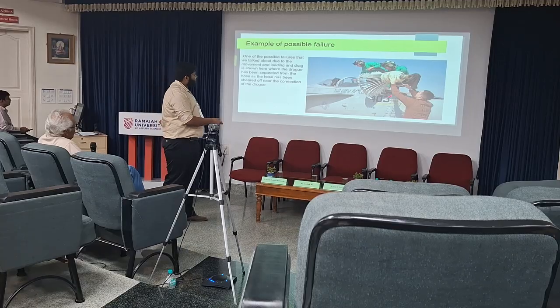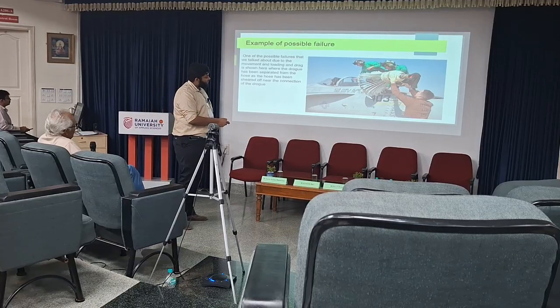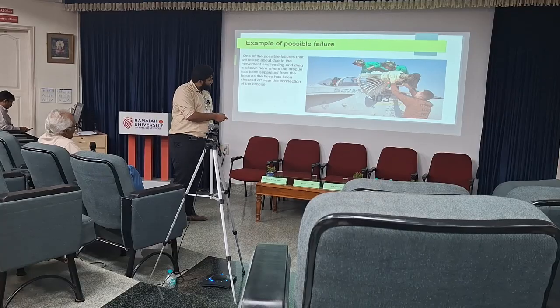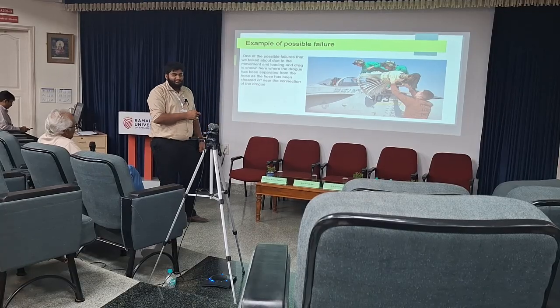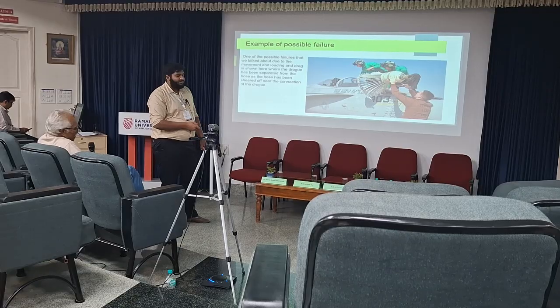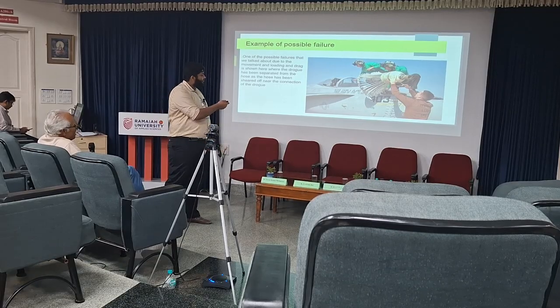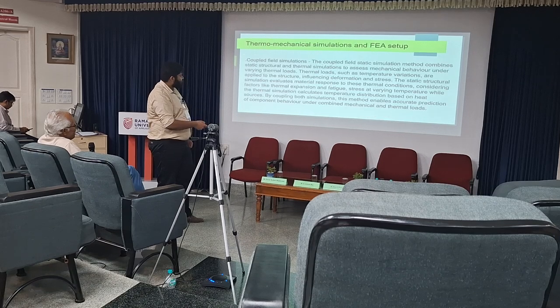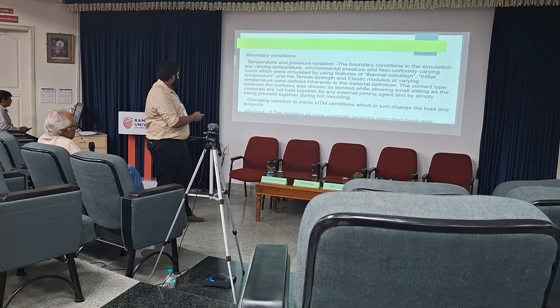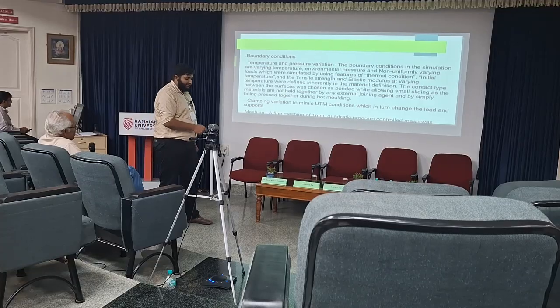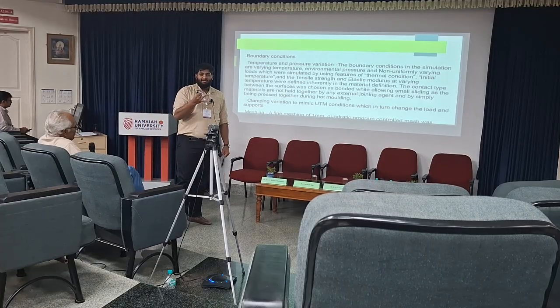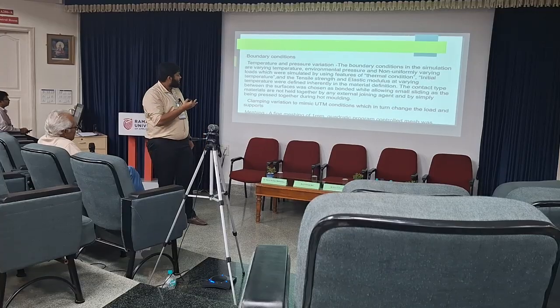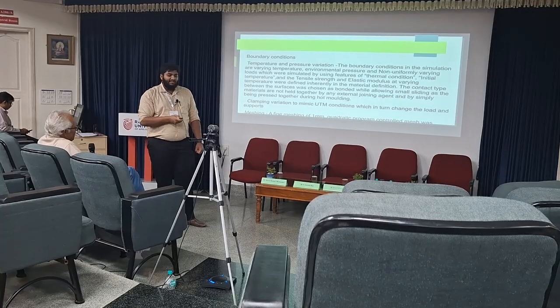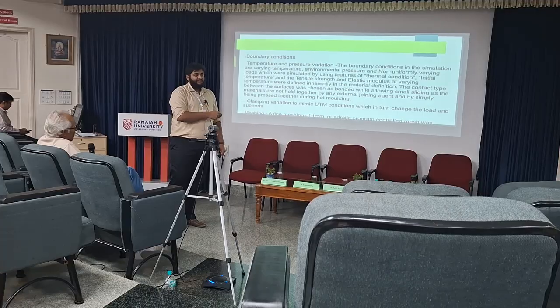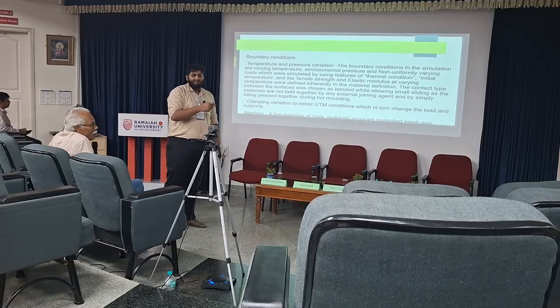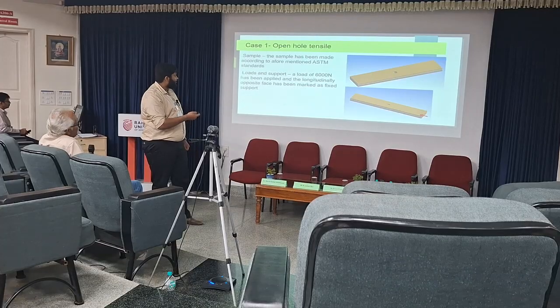so this is one of the possible failures here. As you can see, right at the coupling, the laminate, the hose has been broken. So this is due to fatigue wear that we also have simulated for. So to just put it in short, boundary conditions. So basically, there is thermal condition, there is your initial temperature, environmental temperature, which has all been defined, and then the material strength, which for EPDM at various temperatures has been taken up from literature survey.